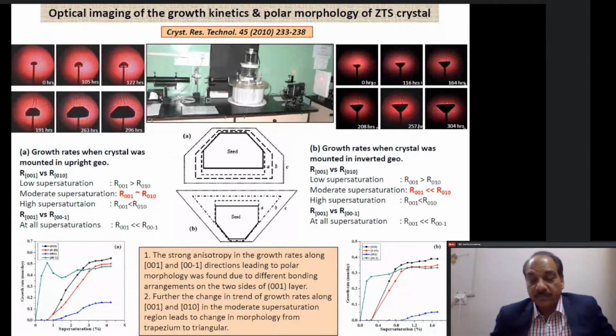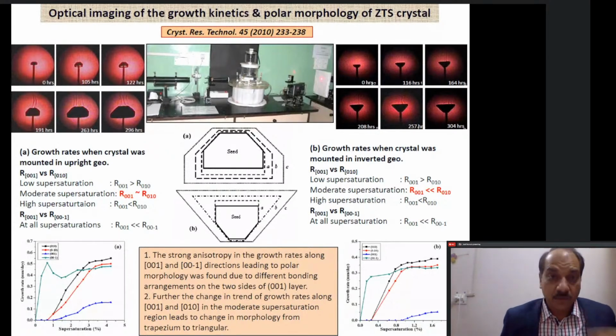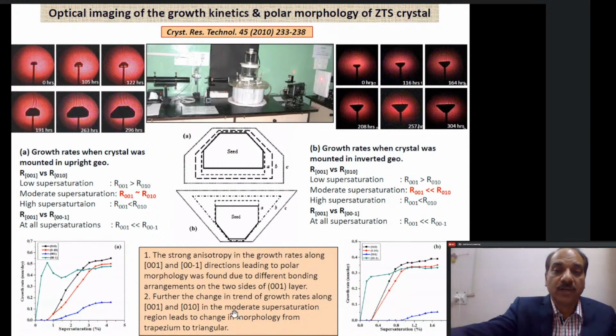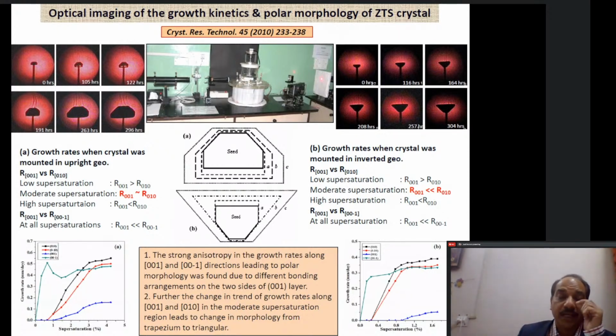Yeah. So we were able to find out how and why there is a change in the morphology of this crystal using shadowgraphy. And we computed the growth rates in an online manner, and these are the growth rate curves on the bottom left and right side of this.